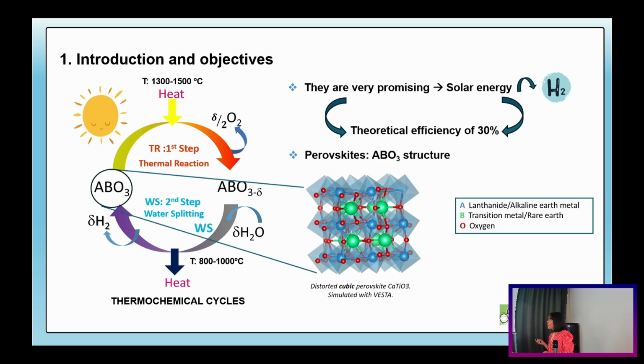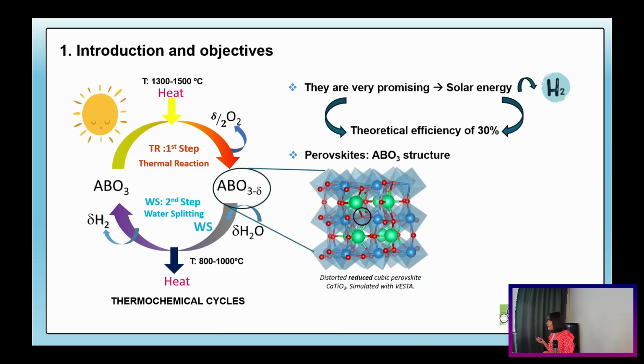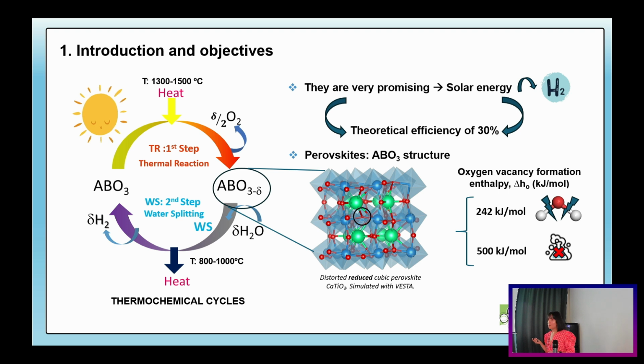In the cycle, the perovskite is reduced with heat, and at this point, oxygen vacancies are formed in the structure. So the reduced species splits water and hydrogen is directly produced. The capacity of the perovskite to form oxygen vacancies in the structure is measured by the oxygen vacancy formation enthalpy, whose ideal range must be between the minimum energy for water splitting and under the maximum energy where no thermal reaction occurs. So we have to find the best candidate of the perovskite that has the best combination of B and A elements to keep in this range of enthalpy.